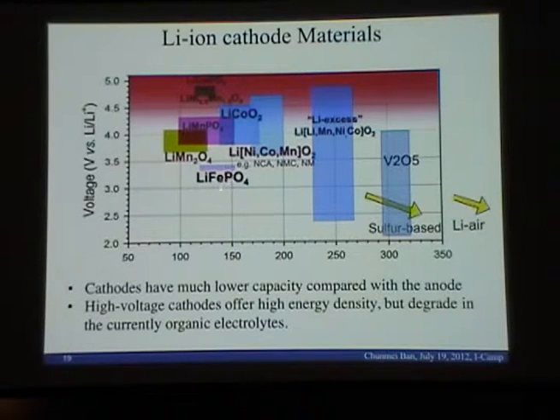And lithium iron phosphate is very popular, because of the low cost of the iron element, and also it's very safe. So lithium iron phosphate has thermal stability. And for lithium cobalt oxide, if you do the calculation of a theoretical capacity, it actually can give 274 if you use 1 mole of lithium in this structure. But the thing is, currently we can only get 160. The reason is we cannot extract all of the lithium from this structure. And the cobalt oxide in the delithiation phase is very reactive.